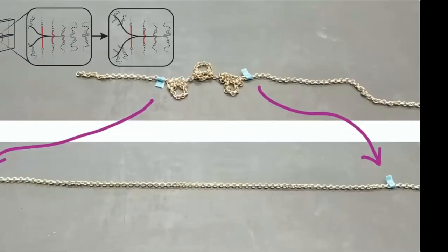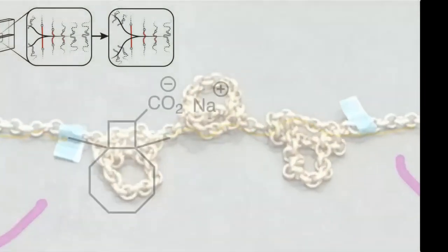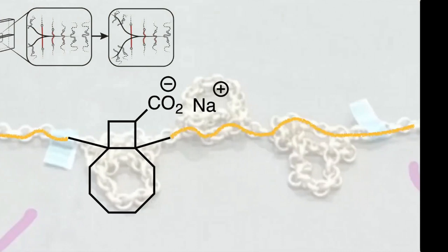And so this drives another what if, right? So what if I take these polymer strands that have multiple loops on them, that at a point when the chain would normally break, instead open the loop to release length and allow that polymer chain to grow longer? What would that mean? And here's where another piece of creativity comes in, because as chemists, as Jeremiah pointed out at the beginning, we're not limited to the molecular structures of the polymers of the past. We can actually design with atomic precision new polymer structures, such as this repeating unit with a little octagon stop sign-like structure that David mentioned, which we've abbreviated BCD, that will respond by not breaking and tearing the chain in half, but, at least at the level of an individual chain, by opening up and releasing that stored length in which we're interested.